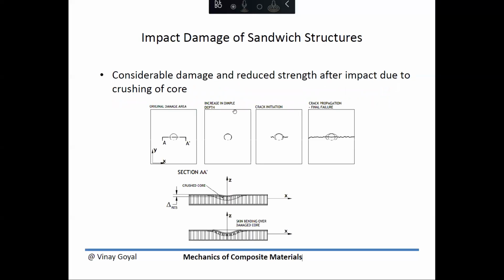Impact damage of sandwich structures can be quite significant. When you have an impact event, it can cause the core to deform. You could also have damage, though not much, on the back side. That's less likely to happen, but it will be absorbed by the core. And then when you apply compression loading, it can cause failure of the face sheet prematurely.